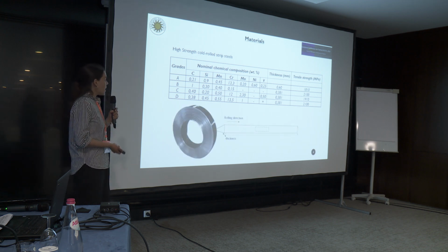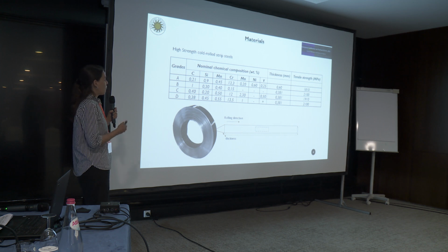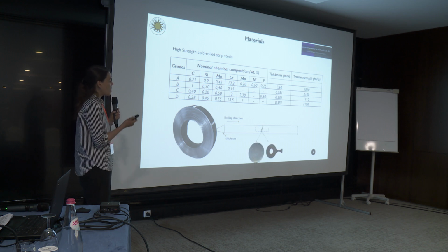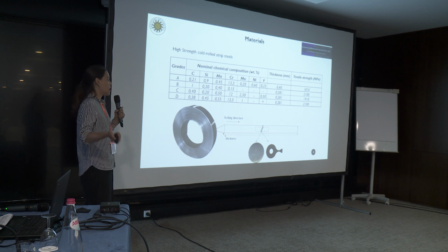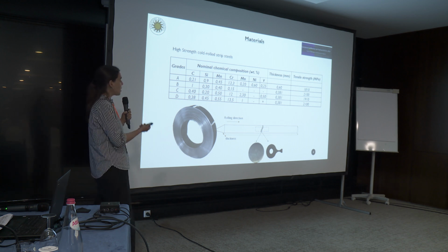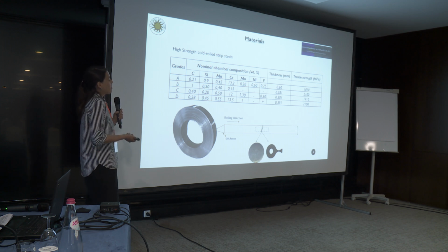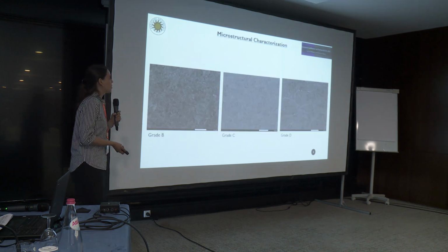For all of our grades, the test specimens were taken from an industrial coil, from the center of the coil, as you can see here. And in both cases, the specimens go for testing. For the microstructural characterization samples, the interest is along the rolling direction.